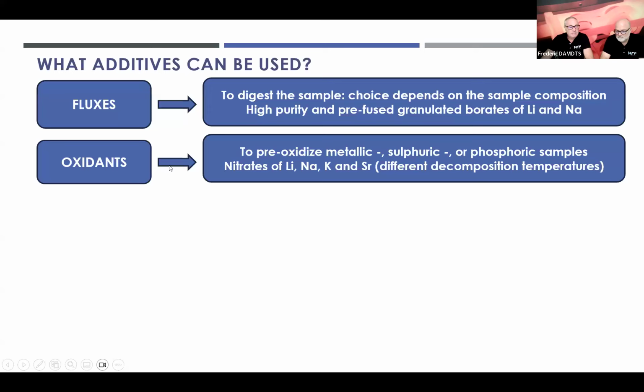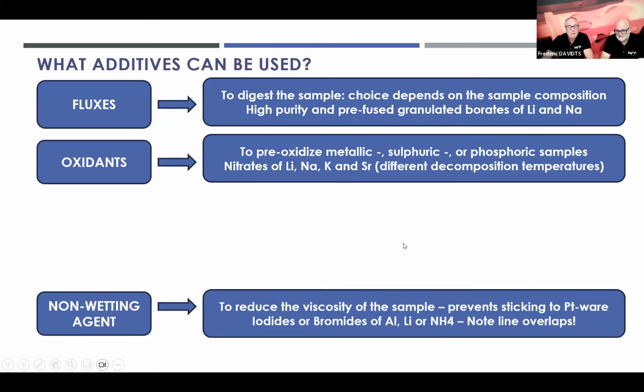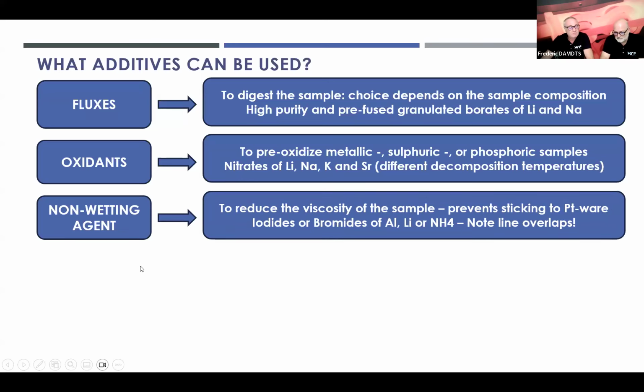The next important additive is the oxidants. These oxidants are there to pre-oxidize especially metallic, sulfuric, and phosphoric samples. In order to do so, we are using nitrates of lithium, sodium, potassium, and strontium, depending on what elements you want to analyze. Lithium nitrate is one that is normally used because lithium, well, we can simply not analyze it with XRF. So that's why this one is a very interesting one. Of course, if you don't want to analyze sodium or potassium, you can also use those nitrates. They have a different decomposition temperature. We will see later in Frederik's part.